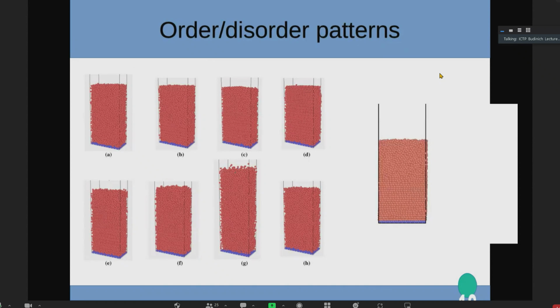Here you have a small video on what is going on in a dry system. We started to pour granular material on top of a smooth surface, and due to gravity, the system tried to move toward the right, and you see that after a specific time, ordering appears in the system. It is starting, yes, completely developed the rheology of the system,